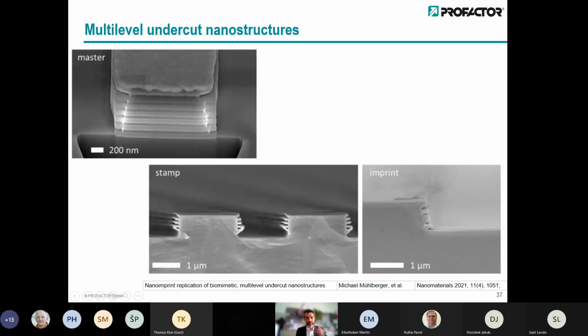And in the end, we also managed to do this for multi-layer structures. Again, here's the master structure. A stamp was replicated and successfully imprinted. You can see these lamellar structures here. One of the big challenges here was the imaging of those structures in cross-section to make sure that you have replicated the undercut. And during sample preparation, most probably some deformations happen. This is why they stick together here.